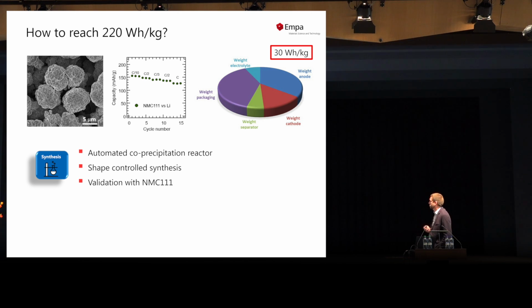So in our lab, we started on the material side. We built an automated co-precipitation reactor for the synthesis of cathode materials. You can see an electron microscope image of these materials here that we synthesize. Actually, we are synthesizing smaller particles of the size of about 100 to 200 nanometers, but we are aggregating them into larger particles using a hydrodynamic process. And it's important that we cluster these particles into larger particles, because that reduces the effective surface of the particles, so we reduce surface reactivity and thereby get better and more stable performance. In addition, these particles have a better packing density, so we can pack more material per volume in the electrode.